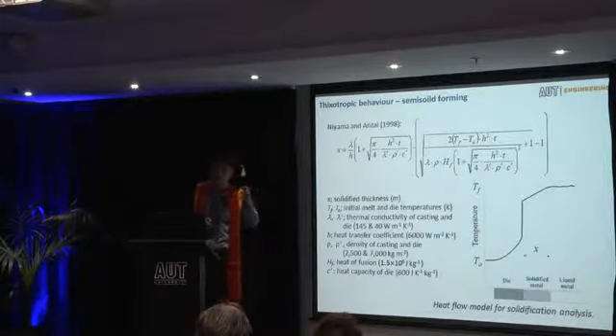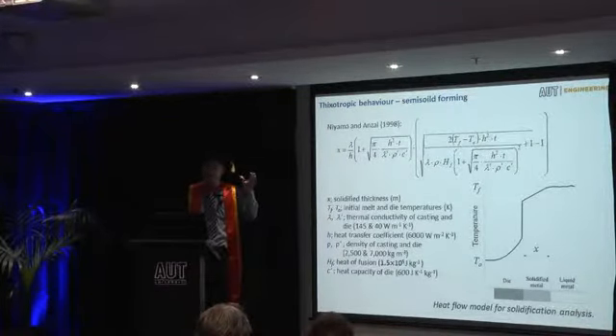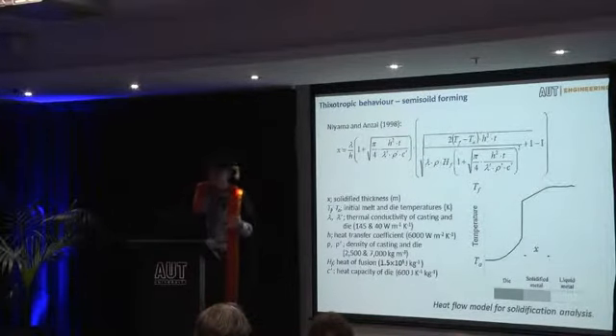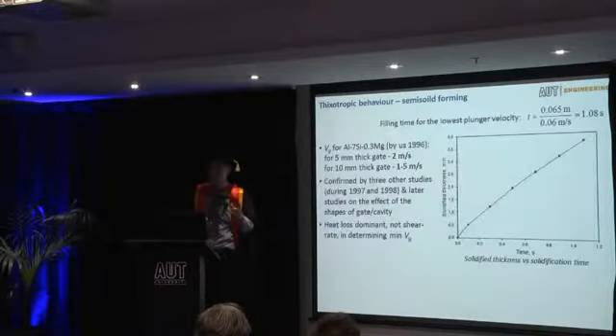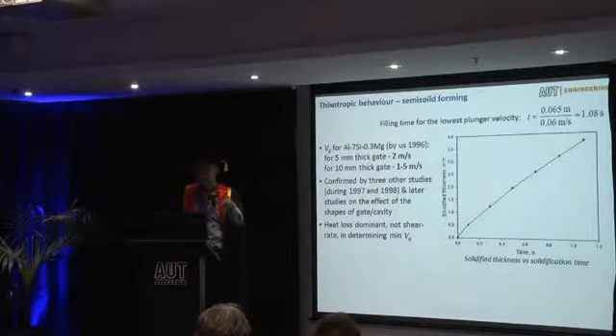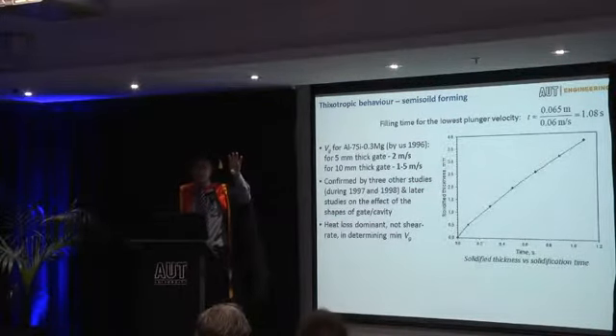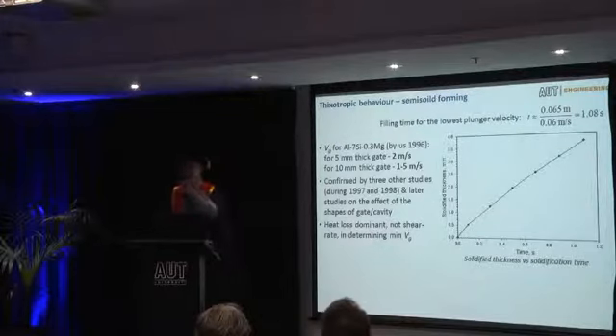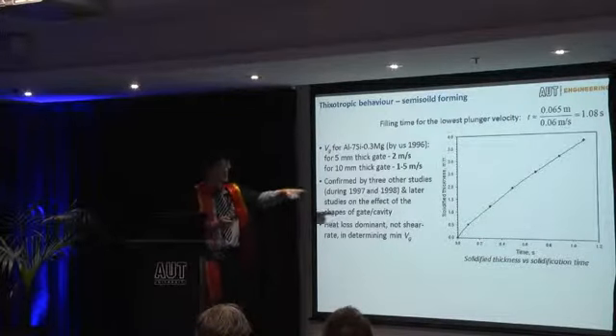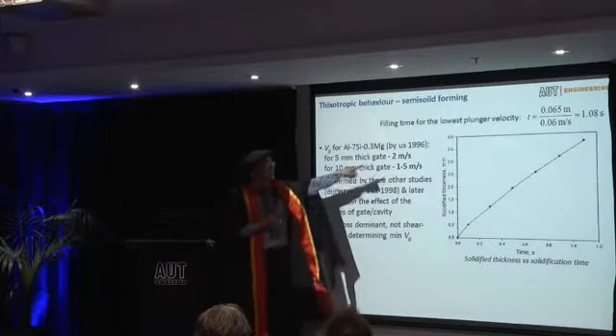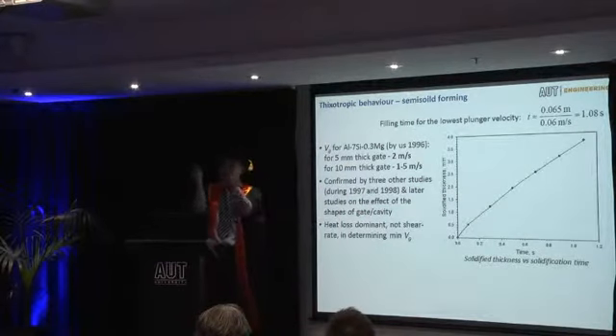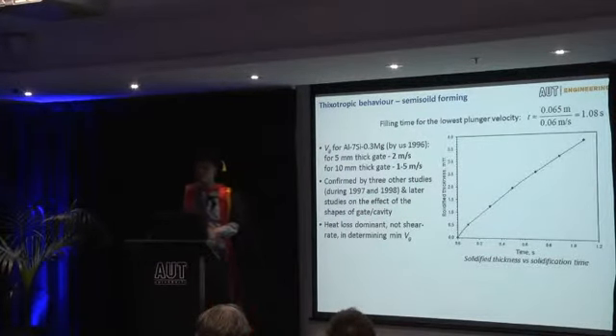But actually, if we go back to the one here, looking at why we have that in that particular condition, we can borrow a formula developed by Professor Niyama. He's very famous for developing a lot of solidification theories. If you do that, you can predict the solidification layer as a function of solidification time, and you can predict that by about 1 millimeter you get to the thickness. It's about the gate choke, so therefore you can't flow anymore.